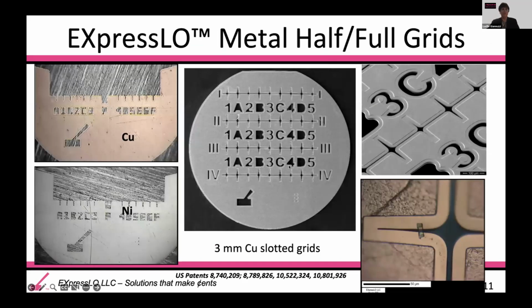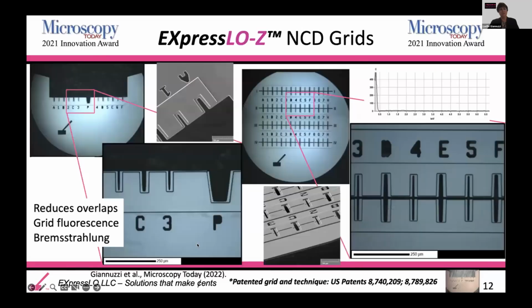microscopy. We also offer a number of different grid materials. We can offer nickel. For EDS applications and materials, ideally, you want to use a grid for quantification and analysis that is not a component of your sample. So we can offer copper grids, nickel grids. We offer half grids, full grids, and we also offer what we call express low Z grids. These are low atomic number grids made of nanocrystalline diamond. The advantage to these grids is that this reduces any EDS overlaps, because you just get a carbon signal. This reduces fluorescence of the grid itself and also reduces the background bremsstrahlung from the EDS signal.